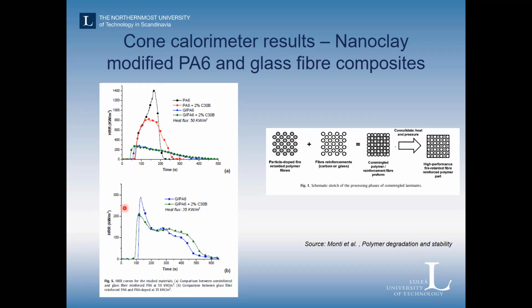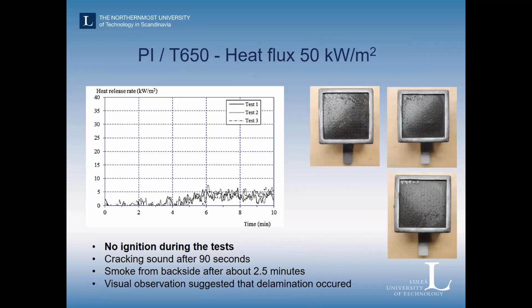By adding glass fiber in a glass fiber composite, we have a similar time to ignition, around 1 minute, and it takes around 10 minutes for it to completely combust, and there is a maximum peak heat release rate of 200 to 300, so it's substantially lower. So this is typical for polyamide composites. If we compare this with the samples that we have produced for our composites, the polyimide with T650 carbon fibers, we notice, again, this is the same curve, but I wanted to show the first one just to give a bit of perspective.